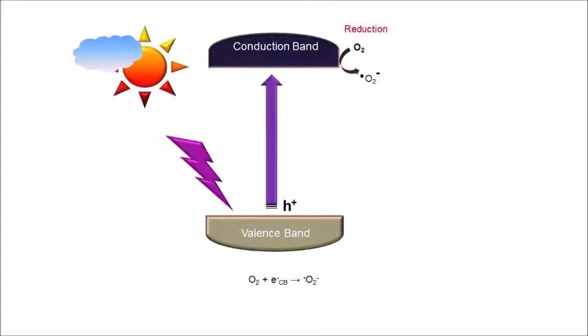Electrons in the conduction band can react with molecular oxygen to form superoxide radical anion. The superoxide radical anions can be further transformed into singlet oxygen. Hydroxyl radicals and superoxide anions produced by the photocatalytic process can degrade the majority of organic compounds until the complete mineralization is achieved. The main limitation for the industrial application of photocatalysis is its wide band gap.